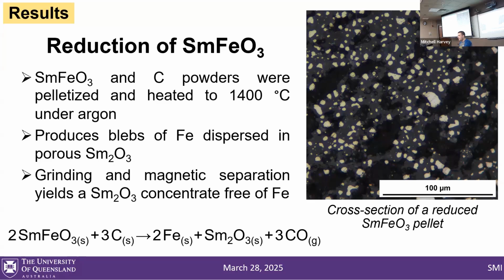And then iron, again, is magnetic. Samarium oxide is not magnetic, or it's at least paramagnetic. And so we can very easily grind and do magnetic separation to get a concentrate that is free of any iron. And you can see that here.